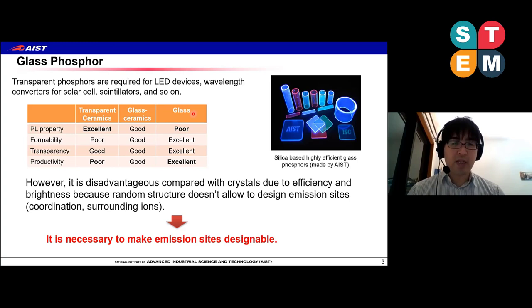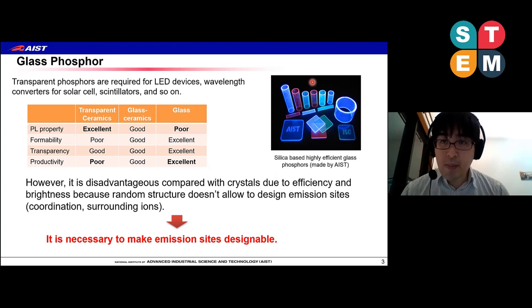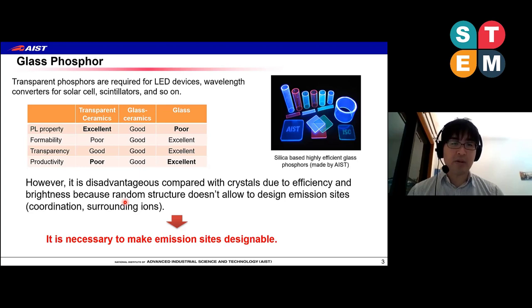On the other hand, glasses have very good formability, transparency, and productivity — better than plastic materials, and very good among inorganic materials. But the problem is that photoluminescence property is very poor compared to ceramics — meaning crystal materials. However, this is a disadvantage compared to crystal due to efficiency and brightness, because a random structure doesn't allow design of emission sites. For example, when we adopt rare earth ions or transition metals as an emission center, we can't control the coordination number and surrounding ions.